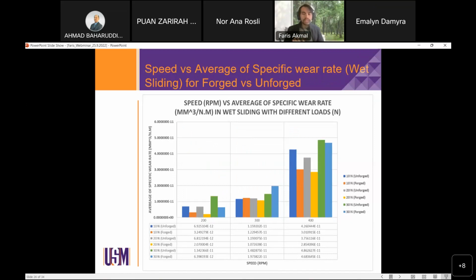This is the result for wet sliding, speed versus average specific wear rate, for forged and unforged cases. As you can see over here, the trend is going from low to high. It means that as speed and load increase, the average specific wear rate for both cases in wet sliding also increases. If you compare both cases, forged also has a lower average specific wear rate than the unforged.